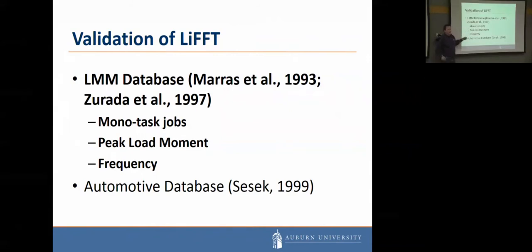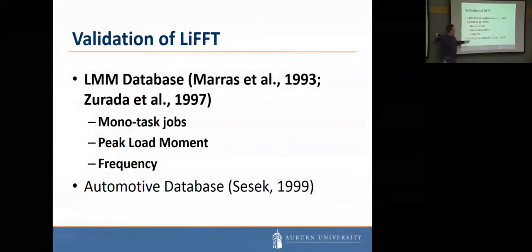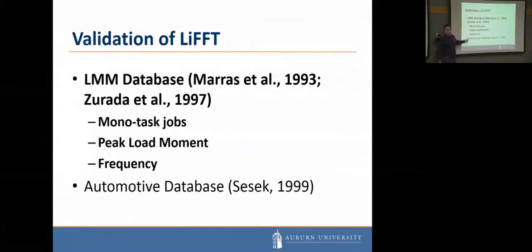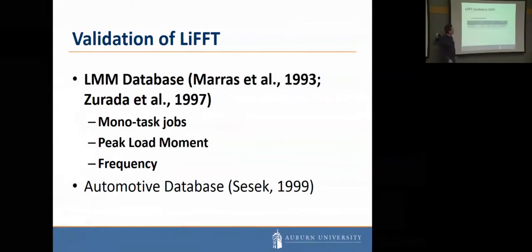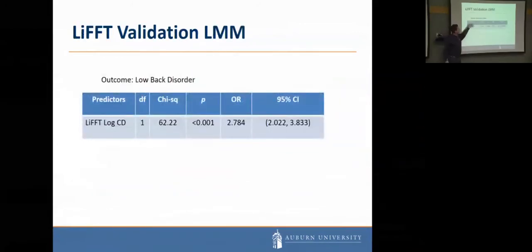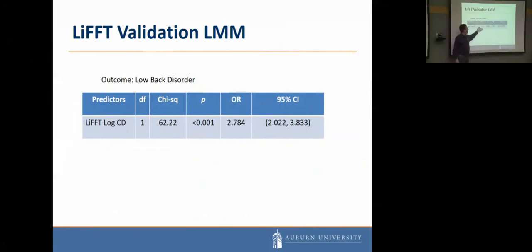They looked at monotask jobs in this case, and they had the peak load moment, which is what we use, and they had the frequency of lifting, which we also used. We also tested against the automotive database. It tested out very well against that as well. But for the LMM, we did a logistic regression model. We found that our chi-square was 62.22, highly significant, with an odds ratio of 2.78.